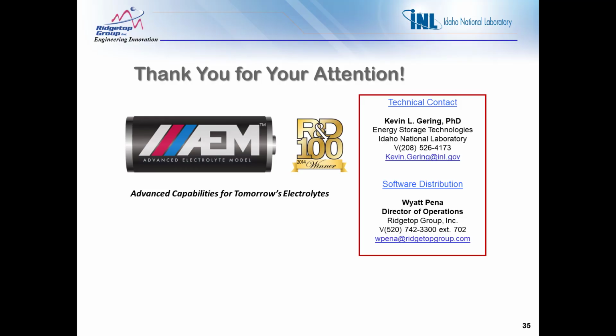So if we do see issues, we can back up and reformulate, use the AEM to do the reformulation, and then take it from there. We've used that approach to greatly accelerate our electrolyte screening for the fast charge program. And it usually takes probably no more than 2 iterations before we're at the place of optimizing the electrolyte for the materials.